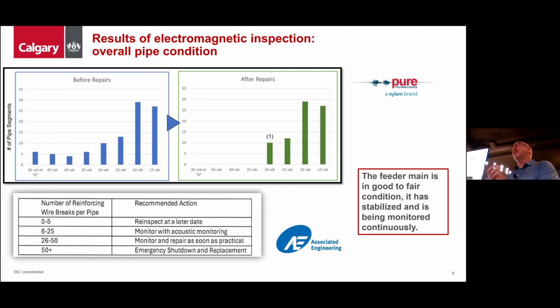We just finished installing it two weeks ago. The acoustic monitoring system is fiber optic. Similar to the pipe diver, we inject the fiber optic with a parachute, and it gets sucked along the pipe while it's in service. We catch it at the other end, pull it out, and then we do it again. We insert another section and keep rinsing and repeating. Then they splice together the fiber optic, so we get a full length of fiber optic.